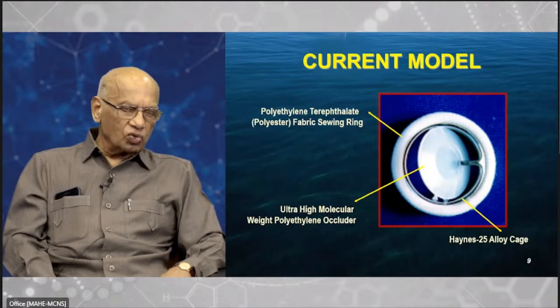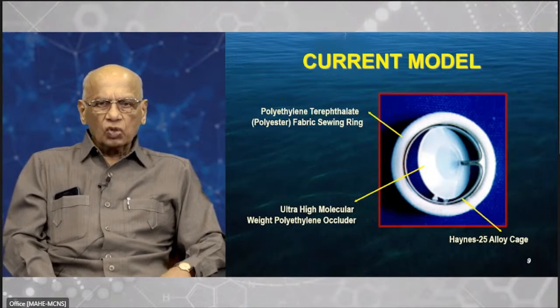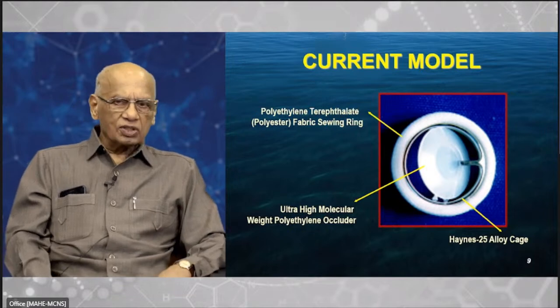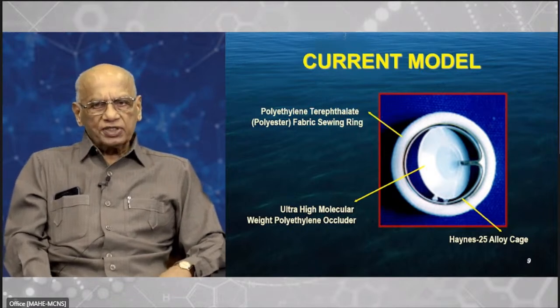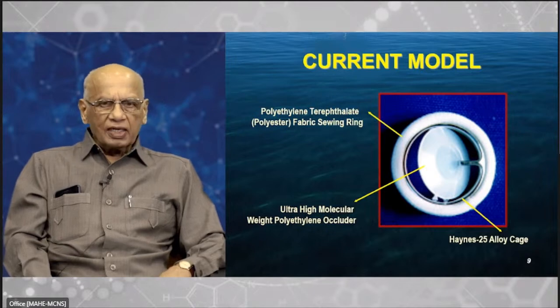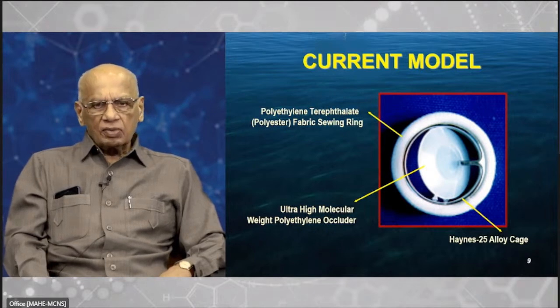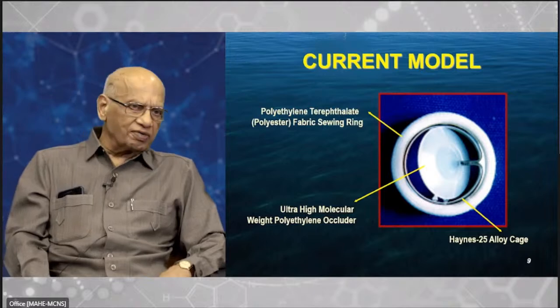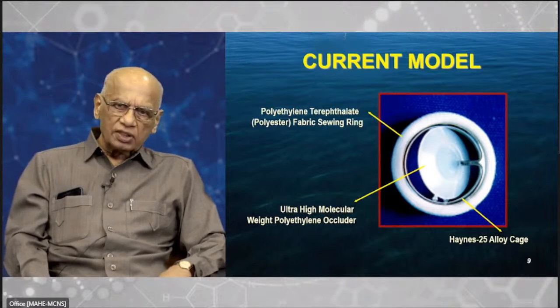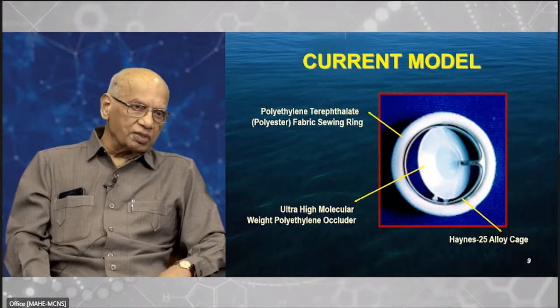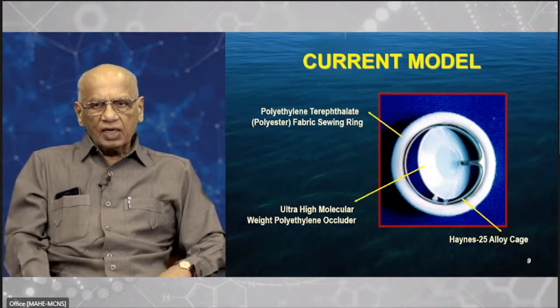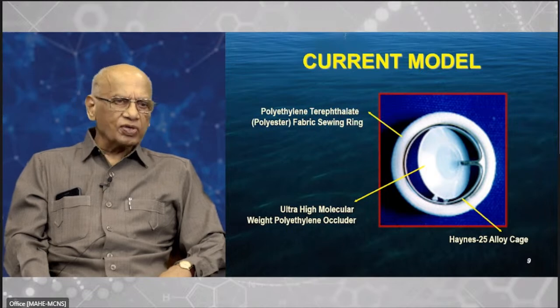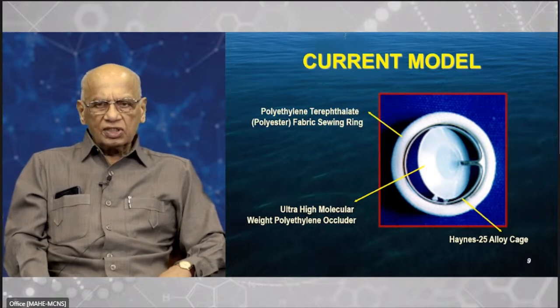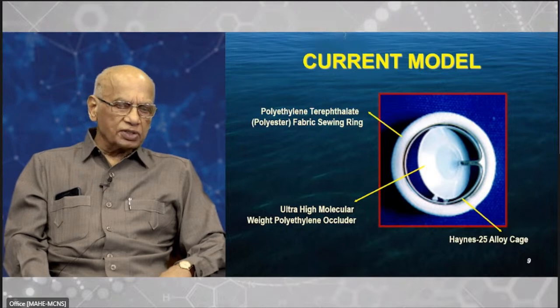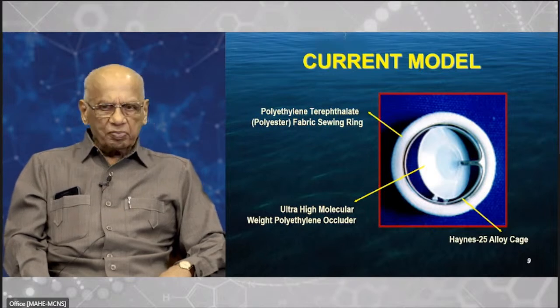That is the current model, the 4th model. Now here the sewing ring remains the same. It's a polyester cloth, warp knitted. There is no change in that. And we have the HAYNES 25 alloy for the housing cage of the valve with no titanium nitride coating. There was no need for it. And the disc is ultra-high molecular weight polyethylene. Now this has not been used in cardiovascular applications. But there is a report of it being used in orthopedics, that we knew.